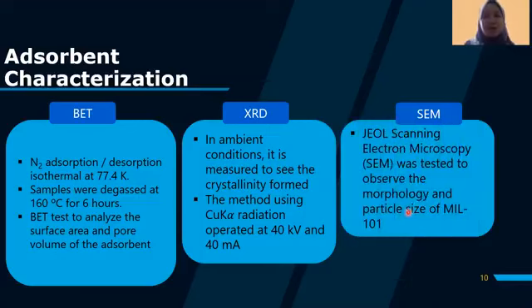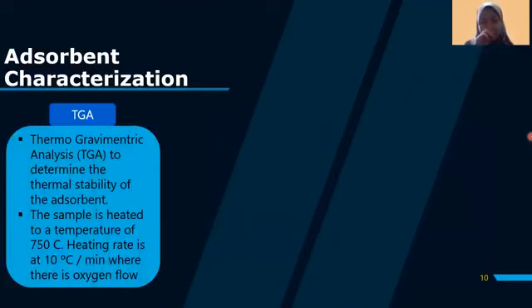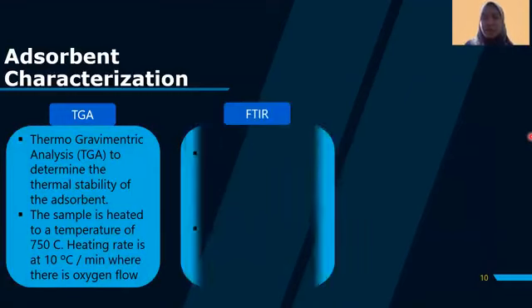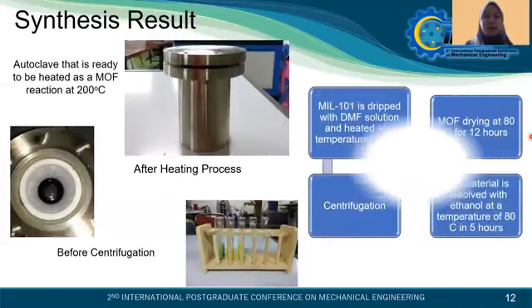So with MIL-101 NDC, to measure the BET, we have to degas for about 160 degrees Celsius for 6 hours to analyze the surface area and the pore volume. And we also observe the XRD and SEM, and we want to observe the thermal stability of the MIL-101 NDC, and after that we observe the chemical functionalities of the MOF. And here are the results of our research.